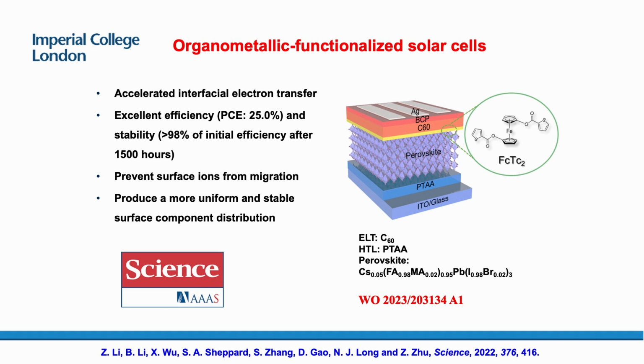So you can see the perovskite devices have multi-layers: electron conducting layers, hole transporting layers, the perovskite itself, but the little, hope you can see it, the little yellow band here was our organometallic material that had not been added as a layer before. So this was the breakthrough result in the field to show that organometallic species could have a role to play. And you can see we've got very, very good efficiencies, but actually it's the stability. The stability after 1,500 hours was already about 98% of the initial value. So there was very little degradation. And this combination enabled us to get the Science paper published.